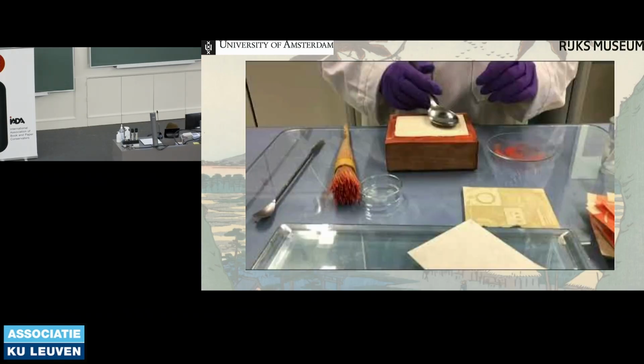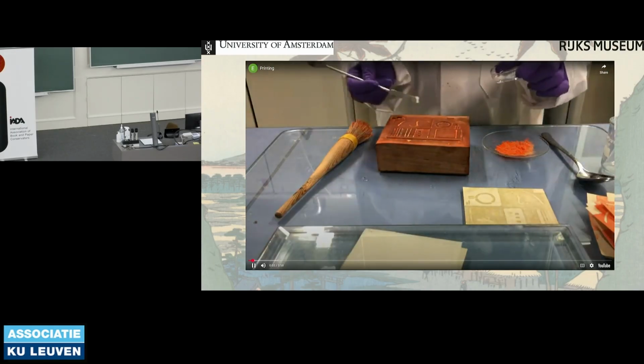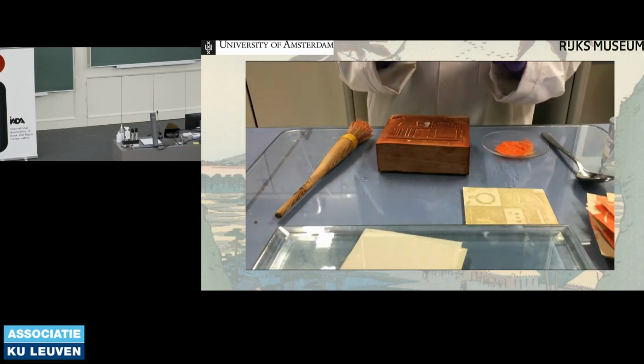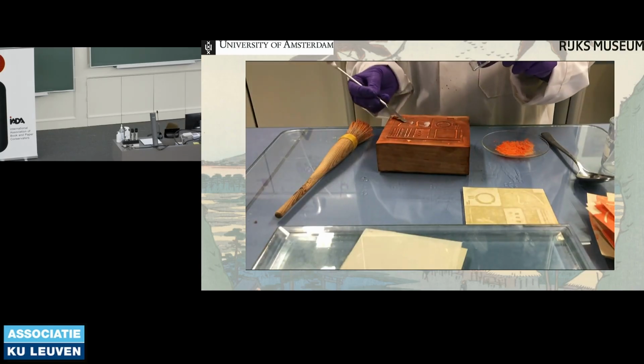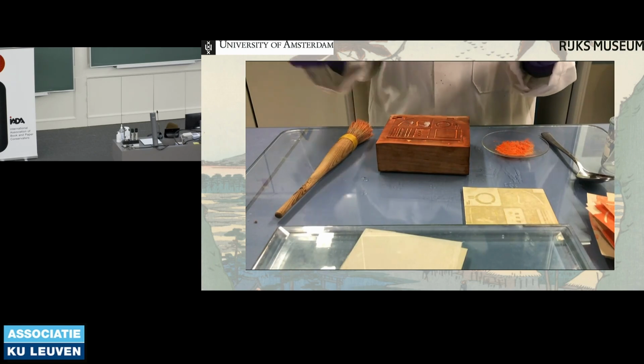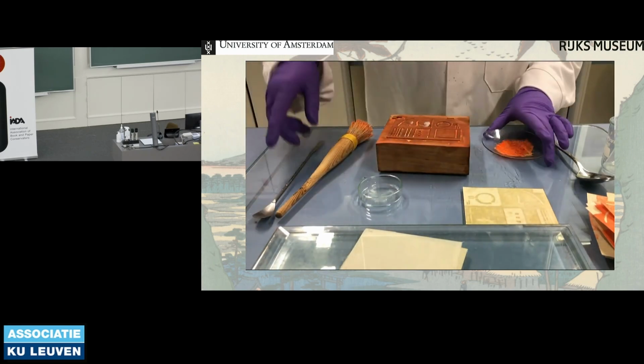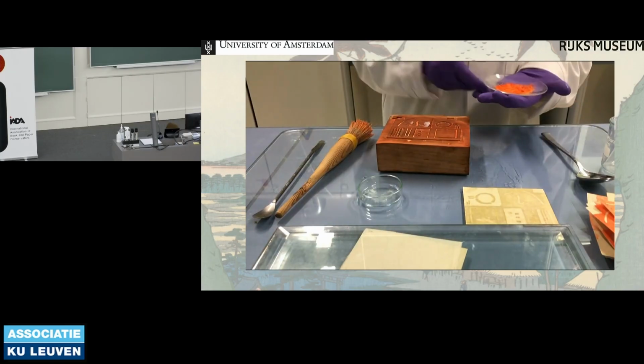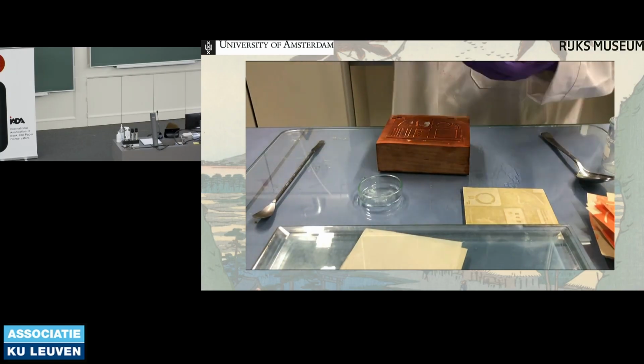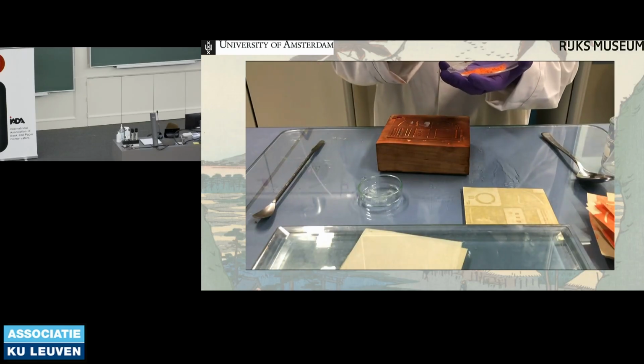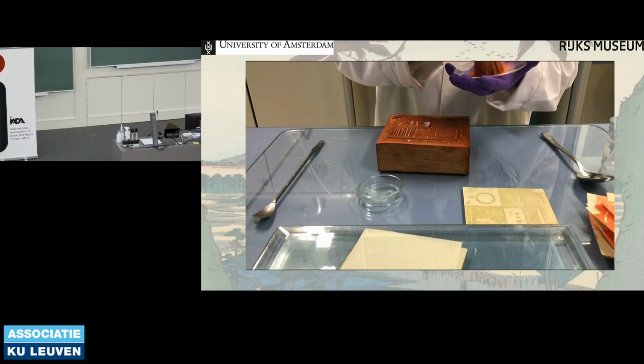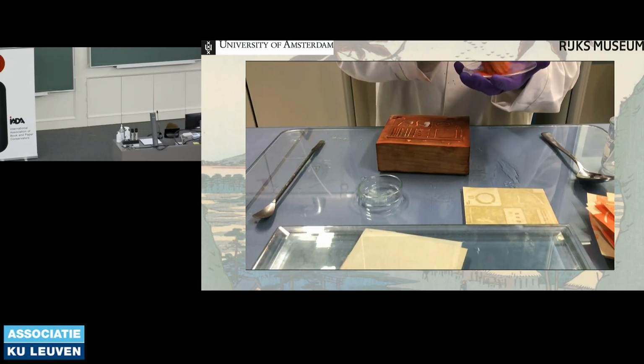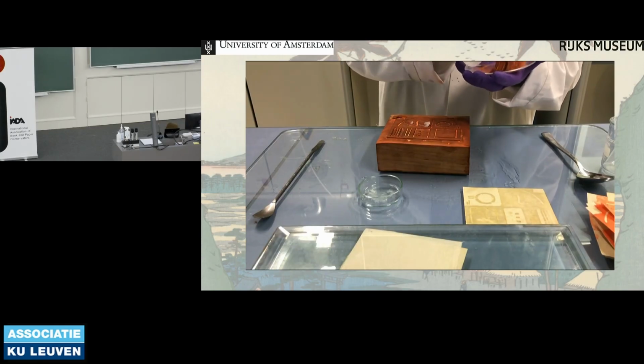So this is the video. Hopefully it plays. Yes, okay. So here you can see me taking the binding agent, which is rice starch paste, and applying it directly to the woodblock. And then I come over here with the brush, and this is the pigment, in this case just pure red lead, and it's mixed with a small amount of water already. And I take the brush, and I mix the pigment and water together quite thoroughly on the brush until I feel like I've picked up most of it and it's combined thoroughly. And then I'm going to apply that brush directly onto the block.